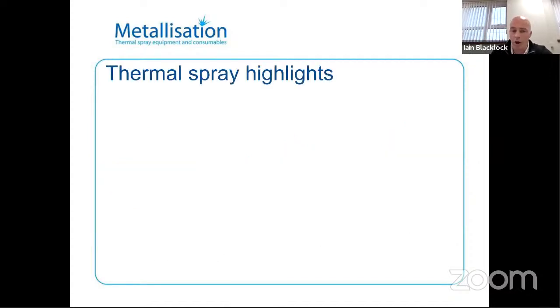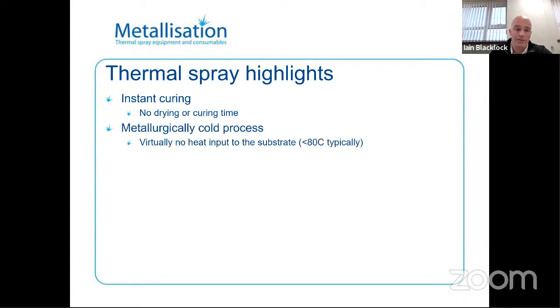So, some highlights of the process. It's instant curing. There's no drying time, there's no curing time. It's not like paint. As soon as it's sprayed, it's cured. You'll never touch it wet or molten. It's a metallurgically cold process, so unlike galvanizing, you get virtually no heat input into the substrate. You wouldn't expect to see more than 80 degrees centigrade heat increase on the steel, and this can be controlled by the techniques that you use for applying the coatings.